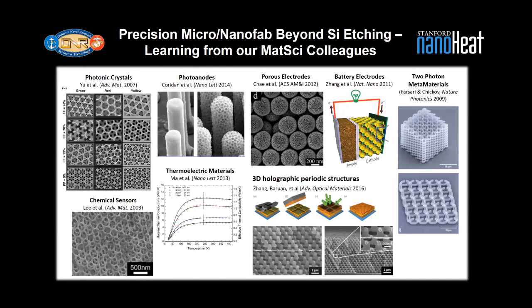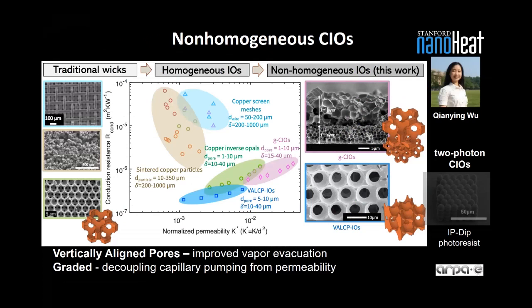And so for example, we have demonstrated, this is Qianying Wu from my group, that you can get very, very low conduction resistance in a porous wick, and you can engineer and control the pore size. And furthermore, you can control the dimensions of the neck, which give you very good fluidic transport and adhesion of the liquid film to the surface and can promote very, very effective boiling.